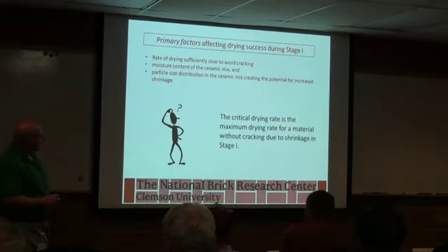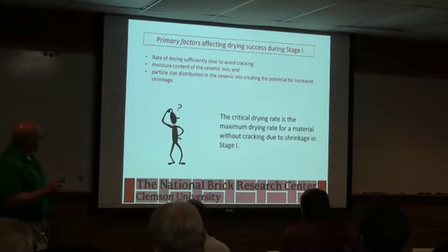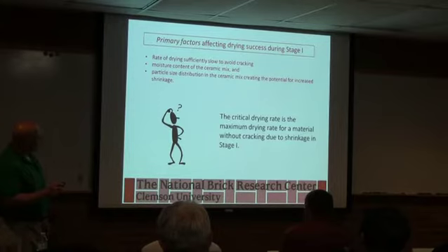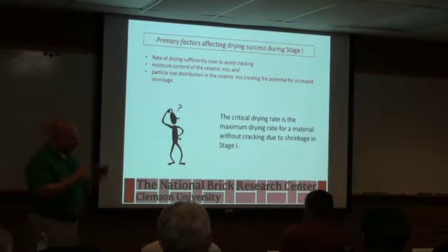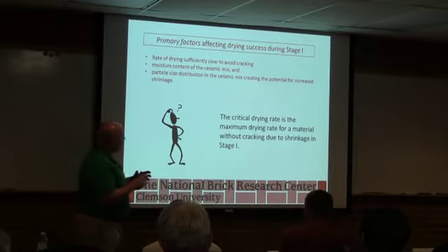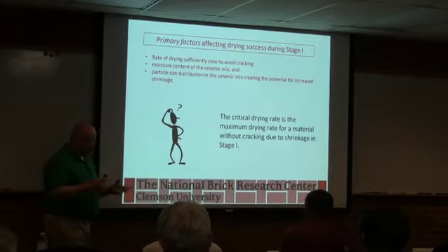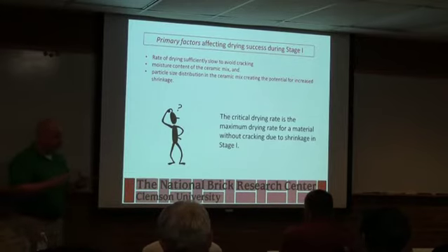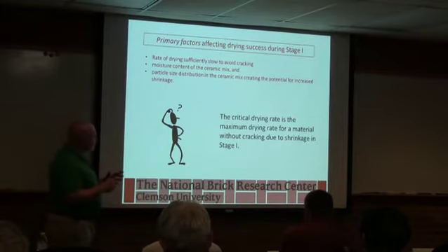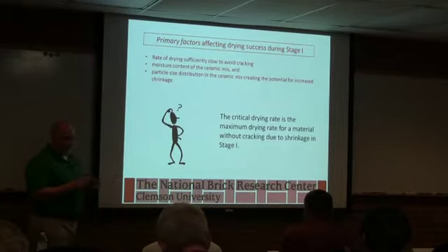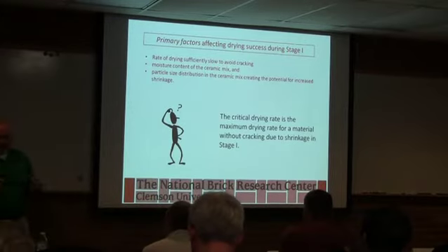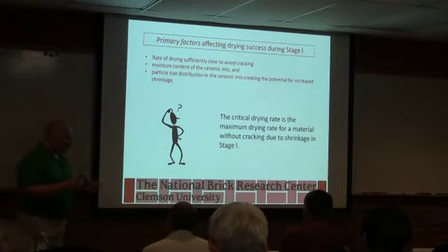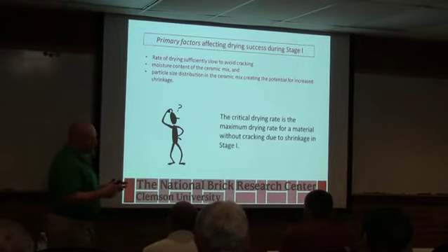So basically the takeaway here is, because shrinkage is taking place in that first part of drying, we've got to dry slowly so that the particles can come together. We don't create excessive pressure in the pores to avoid cracking. We've actually seen in our experimental drying, within a few tenths, based on how fast we dry the brick, we can influence the total shrinkage. So if you dry very fast, this seems counterintuitive, you get a lower shrinkage than if you dry very slow.